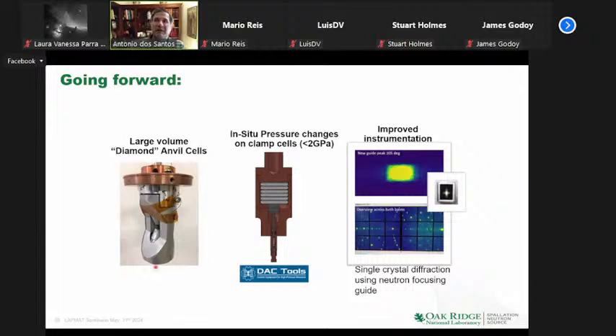We do want to have different diamond anvil cells. As you see here, we want more reciprocal space coverage, different anvils which are cheaper, and now they're coupled vertically so they can be spread over many instruments. We want to change pressure in clamp cells, which we have already achieved in situ. So now you can go to 2 GPa, but instead of taking the cell out for every pressure change, now we can do tens of pressure changes at the same temperature on the same crystal. And of course, we're always improving not only the accelerator, but the instrument. This is the result of a recent improvement with a new guide, and this is a really homogeneous single crystal peak. This is what you can do even from our SNAP detectors, which do not have a huge angle coverage. You have a lot of information from your crystals that you can integrate because the peaks are so well behaved.